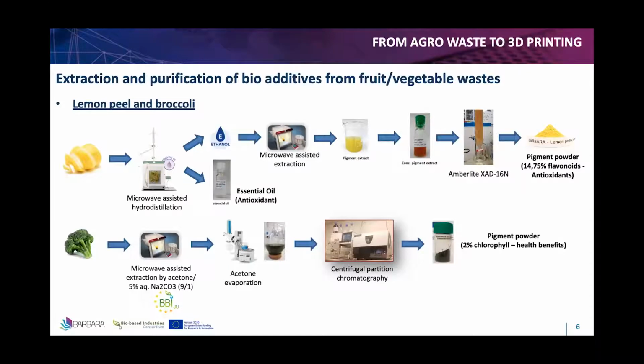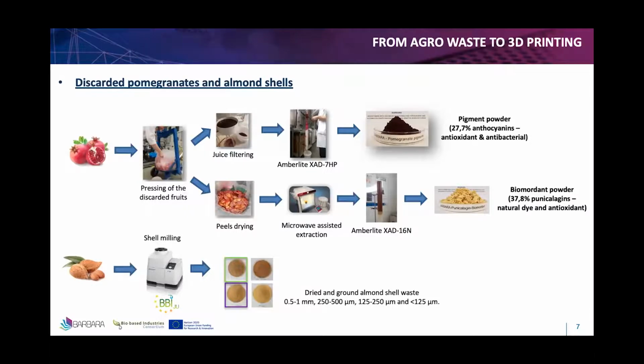From the broccoli as well, using this MAE technology and with acetone and centrifugal partition chromatography, a dark green was extracted. From the pomegranate, two different products were obtained as well. In this case, from the arils, an intense dark pink or red powder was obtained. And from the peels, the biomordant powder was also extracted. This biomordant helps to improve the natural dye fastness of the color into the applied matrix. We could say even that the pomegranate was probably the most versatile agro-residue used, because by varying the pH when fixing this pigment, we were able to obtain a very broad gamut of different colors, from pinkish to grayish.